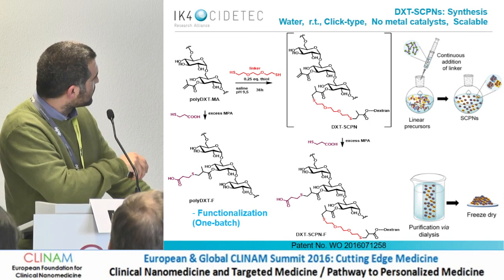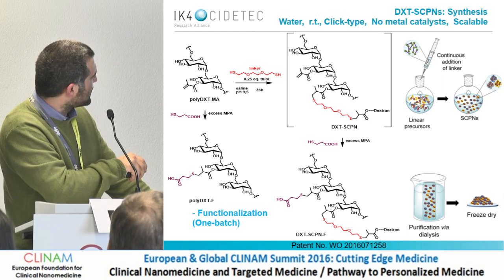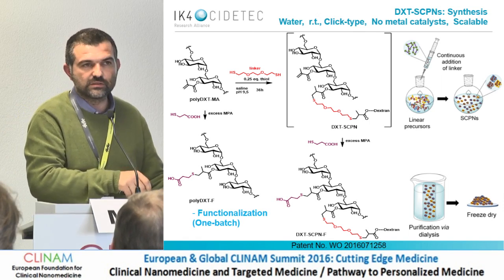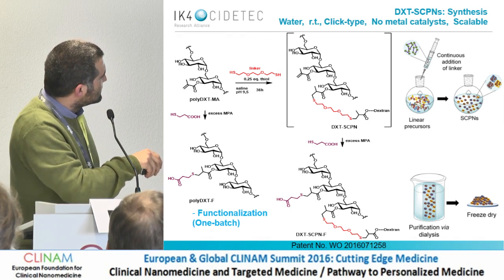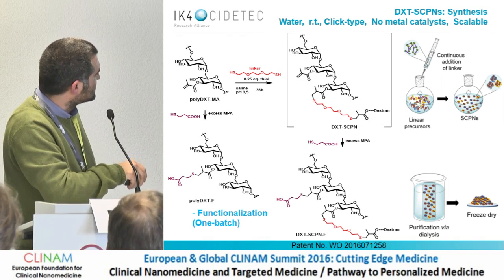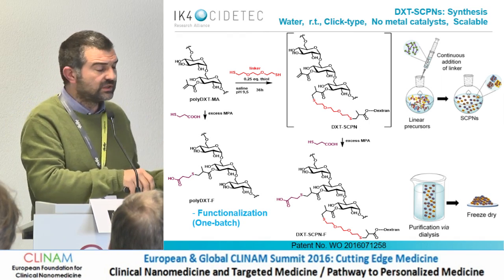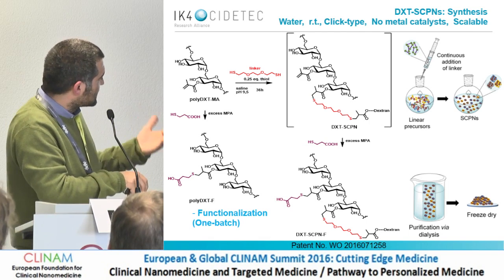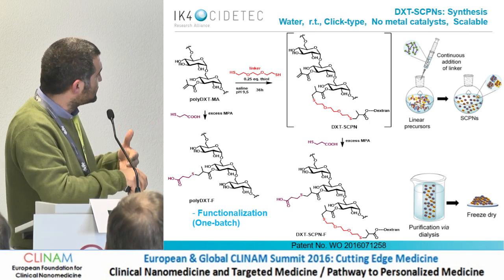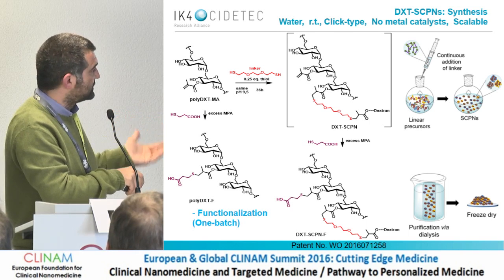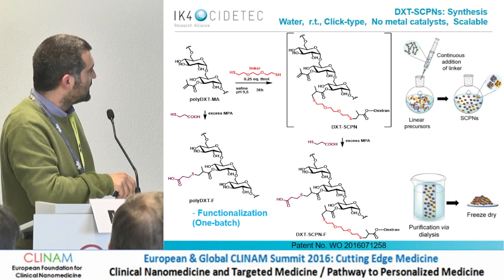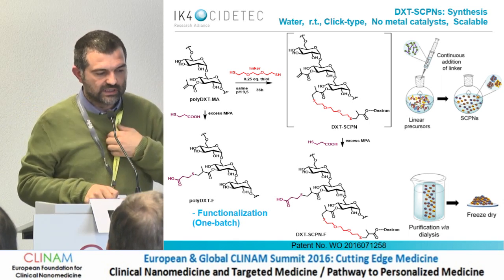By using mercaptopropionic acid we introduce carboxylic groups, which are then used to incorporate biomolecules, drugs, or fluorophores. The nice feature of this reaction is that it runs completely in water — no catalyst, no high temperatures, performed at room temperature, and therefore it is scalable. Purification is done by water dialysis, and the compound can be freeze-dried and recovered.